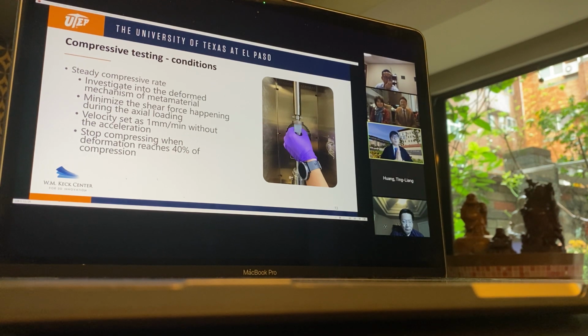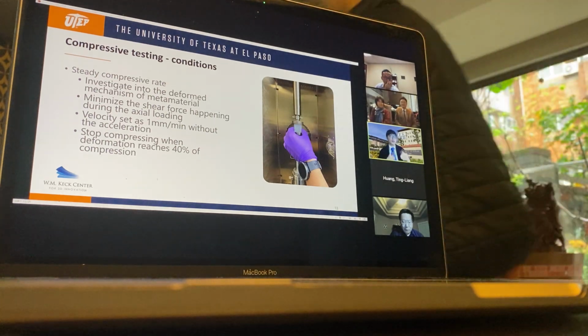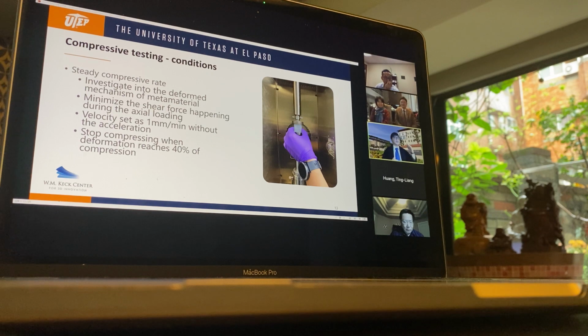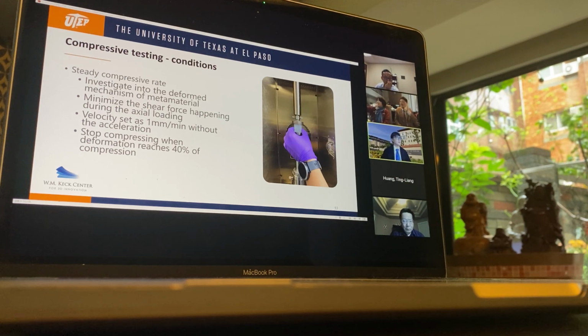As a result, we program the compression to maintain the same velocity. So the velocity we set is 1 millimeter per minute, ending when the total deformation equals 40% of the specimen's original length.